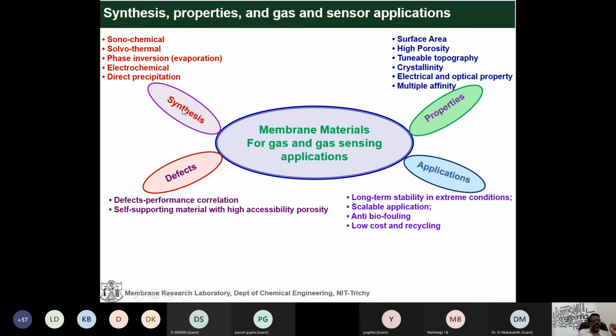You can select good materials, for example any MOF or COF, by sonication, solvothermal, phase inversion, electrochemical, or direct precipitation methods. Any kind of method, you first synthesize the materials. Once you synthesize, you study the surface area, high porosity, tunable property, crystallinity, and other properties. Then you apply them to the membranes. You incorporate them into the membrane by graft polymerization, coating, layer-by-layer assembly, or simple physical blending, which is what we are working on.